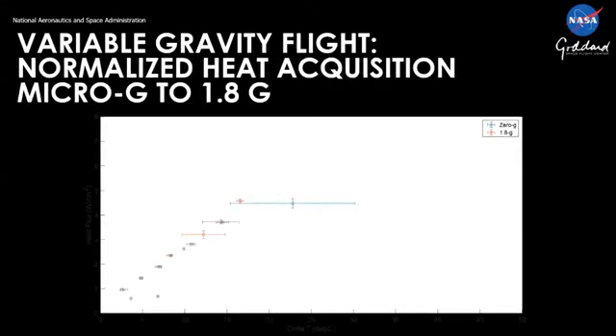This is the data from micro G to 1.8 G, and what you see is, with a couple of exceptions of the baseline data, some 0G points, which we attributed to sloshing. The variable gravity flight is surprisingly rough, and you will get some fluid sloshing. But what you see is the majority of the data falls on the left-hand side, right on top of each other within the error bars. This suggests that with EHD, using both DEP and electrophoretics, or the electrophoretic pump, the coolant pump, you can normalize the heat transfer. And again, I think those of you who are design engineers can see the advantage of that. Next one, Sean.